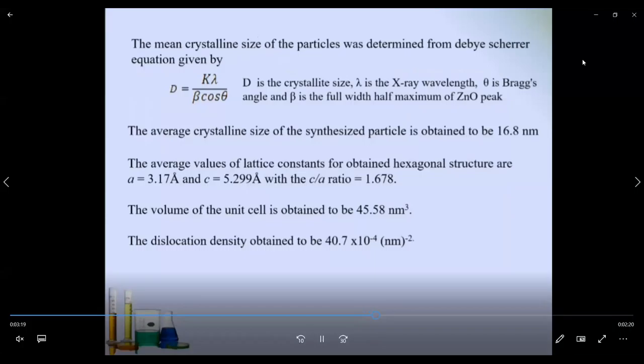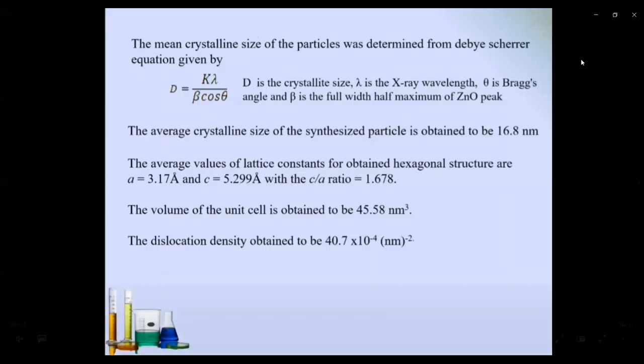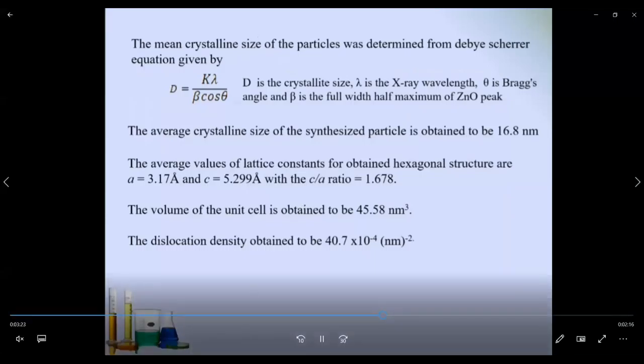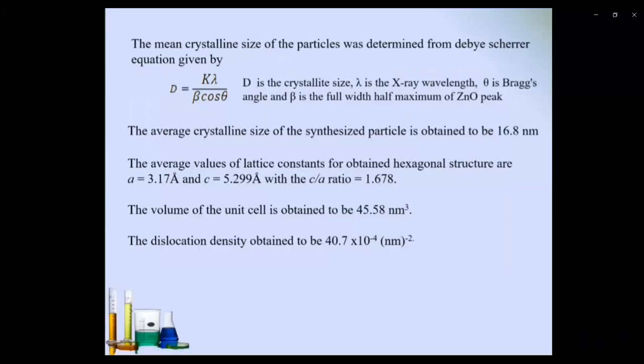The average values of lattice parameters for the obtained hexagonal structure are a equal to 3.17 angstrom and c equal to 5.299 angstrom with the c/a ratio 1.678. The volume of unit cell is obtained to be 45.58 nanometer cube. And again, all these values are compared with JCPDS data. And finally, the dislocation density is obtained to be 40.7 into 10 to the minus 4 per nanometer square.